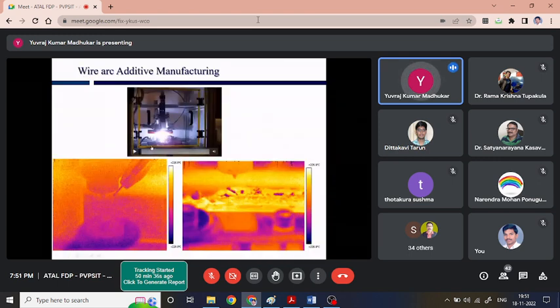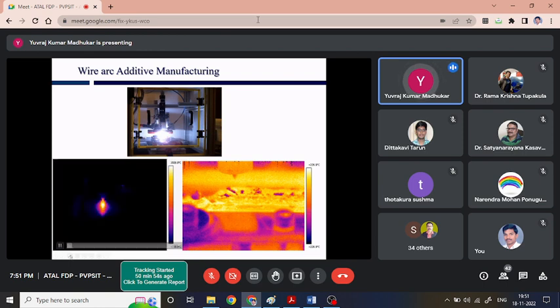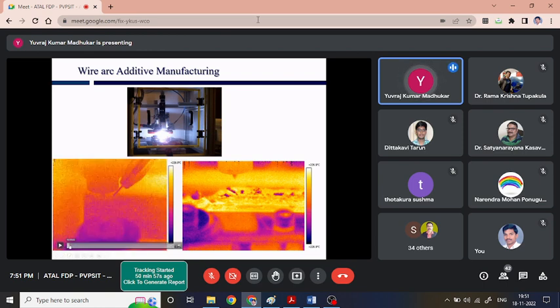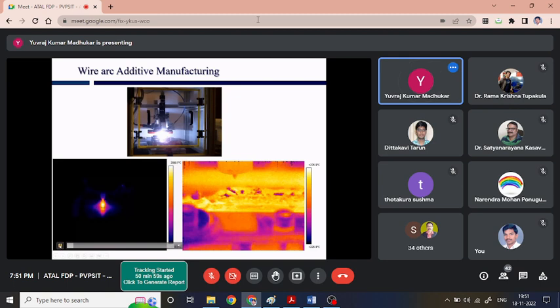Here we can see how gentle this process is compared to MIG. There is no spatter at all, and it's a very gentle process. In a normal VGA-based camera there is a lot of glowing, so we couldn't see how the deposition is going. However, when we recorded it using the thermal camera, here we could see that first the arc has been stabilized. Then we feed the wire into the stabilized arc of the TIG. And we get a very nice bead just behind it. There is no spatter at all.